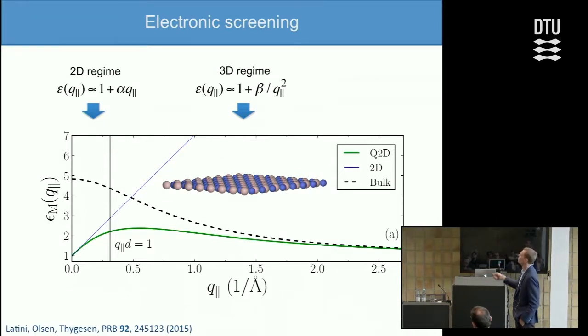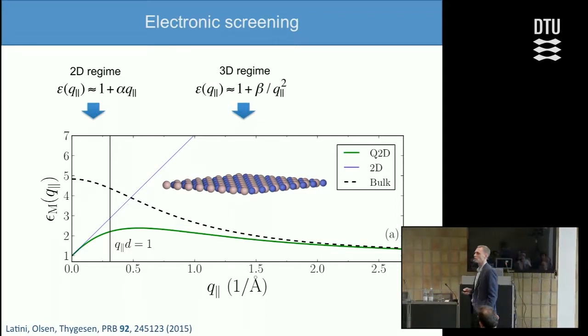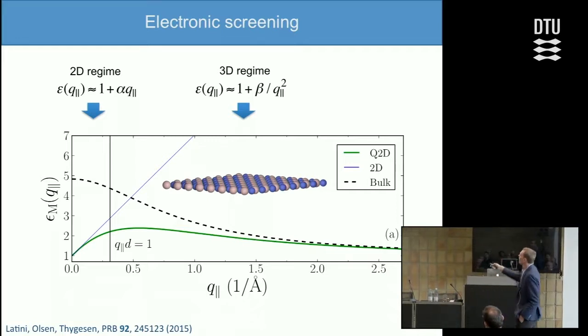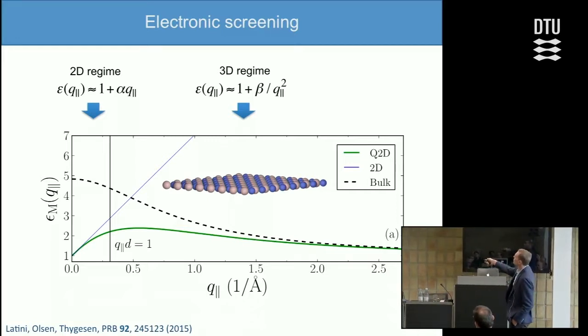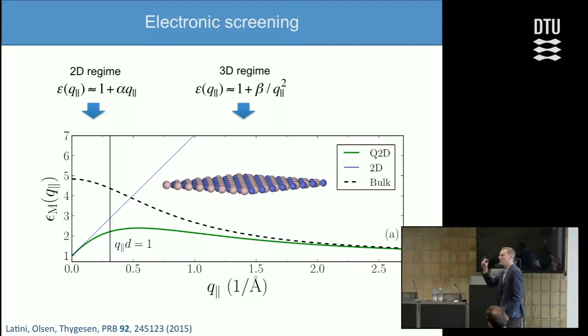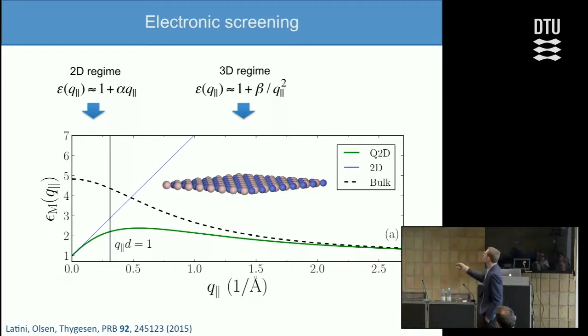And mathematically, this means, if we look at what is called the dielectric function as a function of wave vector q, that for a 2-dimensional material, we get the green line. This is hexagonal boron nitride, a single layer - that's the green line, that's the static dielectric constant, and the dashed line is bulk hexagonal boron nitride. We can see for large Q vectors here, where Q is larger than the inverse thickness of the material, the screening properties are similar to in 3 dimensions.